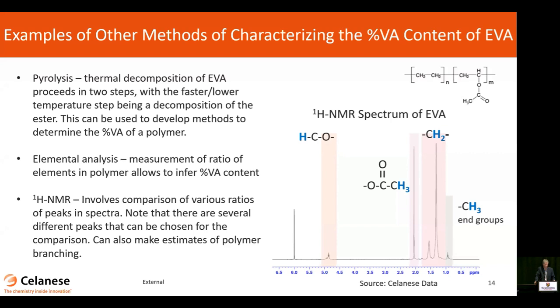I think a more practical one to consider here is probably proton NMR, right? Many laboratories will have an NMR. You can develop methods here based on comparing the relative intensities of various peaks in the structure. The other nice thing is that in proton NMR, you can get a peak for the CH3 end groups associated with the polymer. We'll talk about that more in a little bit when we talk about branching of the polymer, because that allows us to characterize the branching of the material.